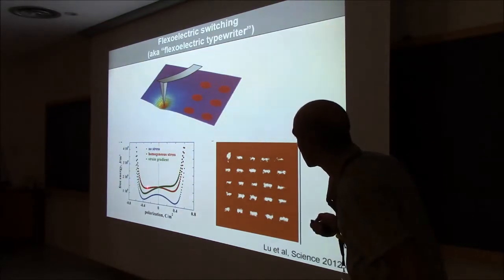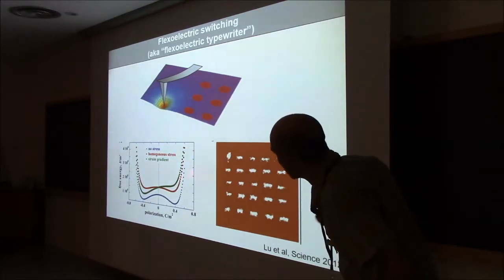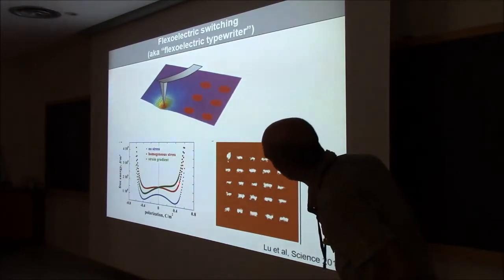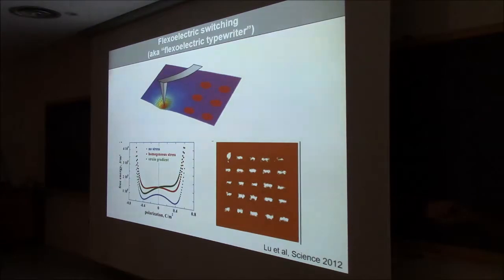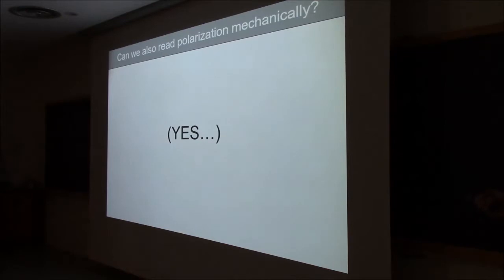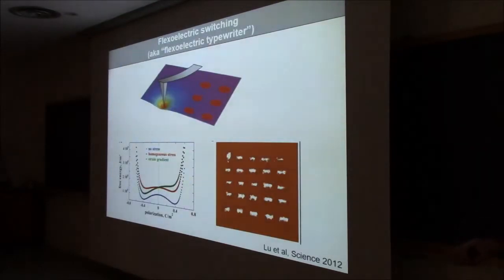If instead of homogeneous stress I put inhomogeneous stress, a strain gradient, then if I had been on this polar state, the strain gradient will make me switch to that state. And experimentally, you can do this by taking your BTO thin film with polarization up, and you push with the tip of an AFM. It doesn't even need to be metallic. You don't connect it to a voltage, because the whole idea is that you want to do it without a voltage, and you can achieve some voltage-free switching. So this is for writing polarization.